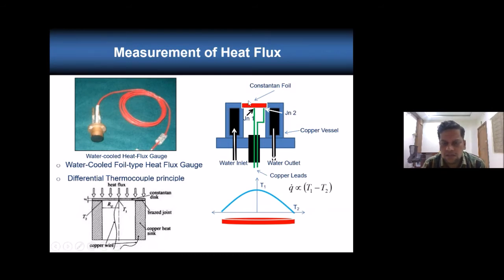Now on this side, at the center we will have a constantan foil, microns thick. This constantan foil is welded with two copper wires, one at the center, the other one at the edge. The edge of the constantan foil is always cooled with water. You can see here, this is the water inlet and outlet. So we always have to maintain the edges at room temperature. The center of the foil will experience the maximum temperature.